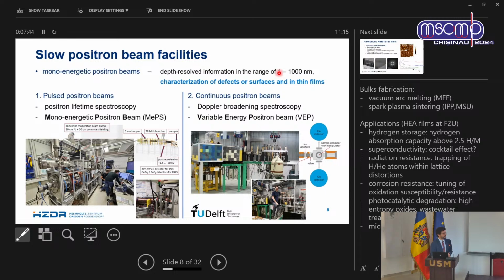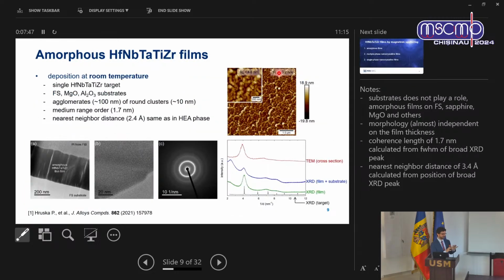The first kind of result is what happened when we used the very basic deposition conditions and deposited the films of hafnium, niobium, tantalum, titanium, zirconium on an unheated substrate at room temperature. The resulting structure has this morphology, and the TEM observation confirmed there is no long-range ordering of the atoms because of the low temperature of deposition. So we have just an amorphous film with clusters of atoms, and only ordering within the range of, let's say, 1.7 nanometers. That's the coherence length of these clusters.